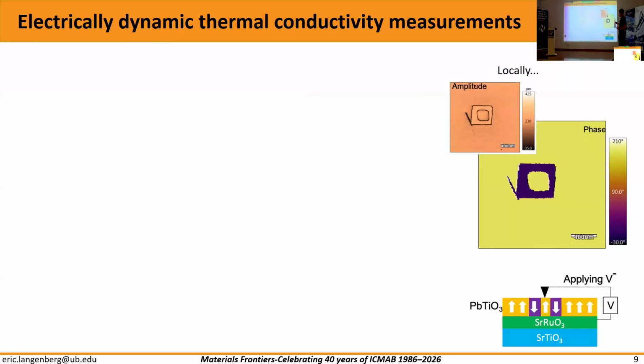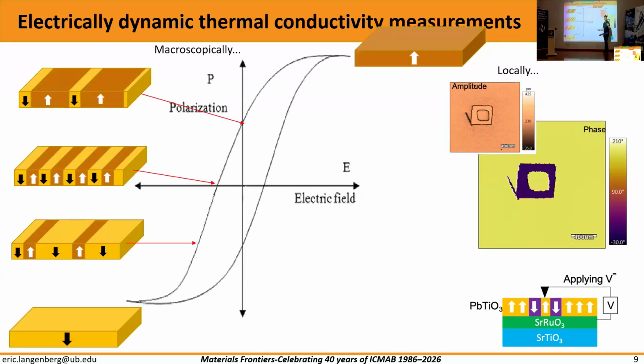With a PFM, I can write on the lead titanate films, and we can put domains and domain walls easily, but locally. So if we want to do it at room temperature in a lead titanate film, at 5 nanometers, I have seen very few reports of a polarization hysteresis loop in an epitaxial lead titanate film of 5 nanometers. They are basically quite leaky. So it's very difficult to do that. And that's why we moved to another material.